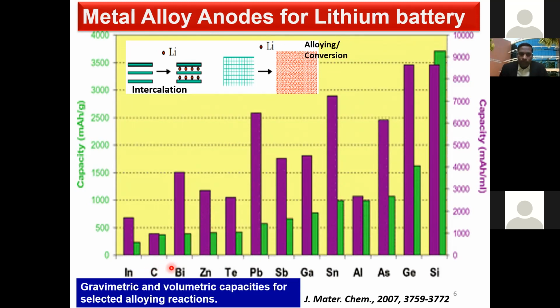We have several options: bismuth, tellurium, lead, antimony, gallium, tin, and the very attractive ones are tin and silicon. You can see that their theoretical capacity is as high as 3,500 or close to 4,000 mAh per gram. And the volumetric capacity is very high, 10,000 mAh per ml, which, if you look at the energy density, is almost closer to that of gasoline per liter. So it's going to be